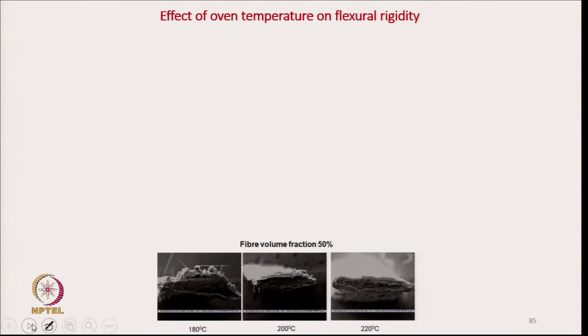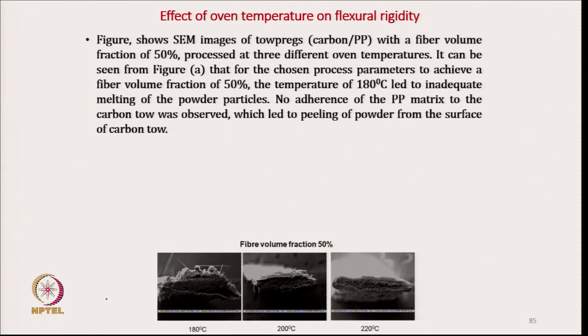So, effect of oven temperature on flexural rigidity, if we see, as we have mentioned here, the scanning electron microscope picture with the fiber volume fraction 50% here. It can be seen that for the chosen process parameters to achieve the fiber volume fraction 50%, the temperature of 180 degrees led to inadequate melting of the particle. So, no adherence of PP matrix to the carbon tow was observed, which led to peeling of powder. We can see very clearly the powder gets peeled off.